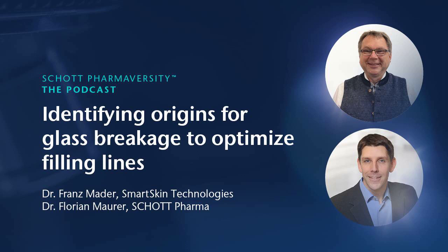First of all, as a matter of fact, glass has a high intrinsic strength. But this high intrinsic strength is reduced by flaws and damages on the surface and in the volume of the glass. You can compare this behavior to a chain. When being pulled apart, a chain always fails at its weakest link. A strong chain then consists of strong, intact links, representing the high intrinsic strength of glass. Now, flaws and defects weaken the glass. In comparison to the chain, this would mean that weaker or damaged links are introduced. When being pulled apart, the chain now fails at much lower tension, and so does a flawed or damaged glass. It really breaks at lower mechanical loading because of its reduced strength.